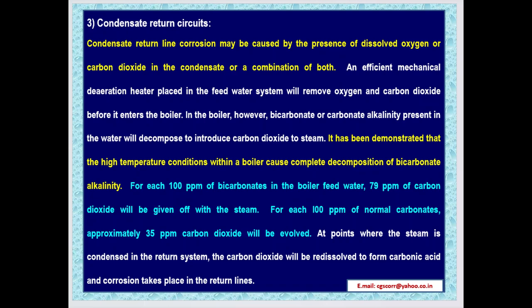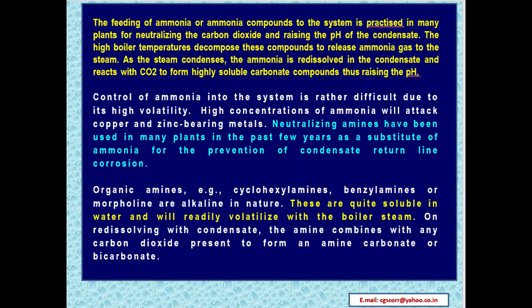At points where the steam is condensed in the return system, the carbon dioxide will be redissolved to form carbonic acid, and corrosion takes place in the return lines. The feed of ammonia or ammonia compounds to the system is practiced in many plants for neutralizing the carbon dioxide and raising the pH of the condensate. The high boiler temperatures decompose these compounds to release ammonia gas to the steam. As the steam condenses, the ammonia is redissolved in the condensate and reacts with carbon dioxide to form highly soluble carbonate compounds, thus raising the pH.